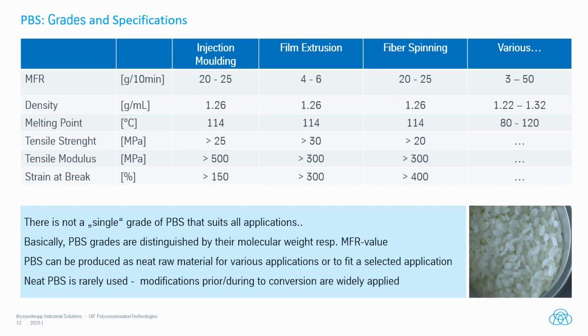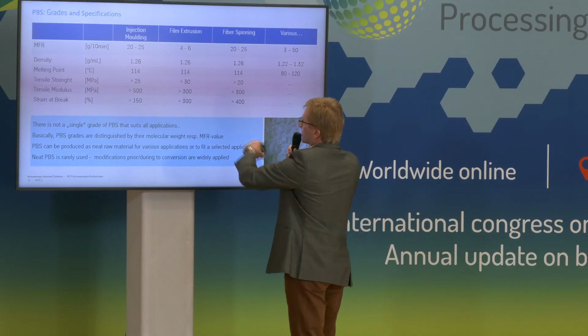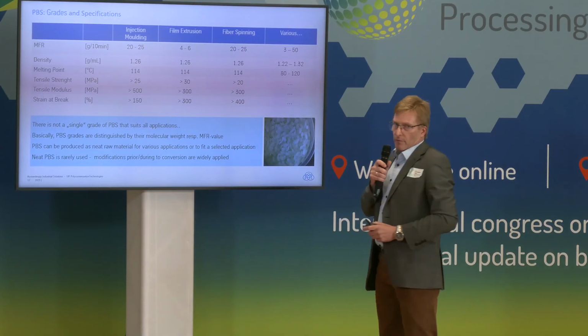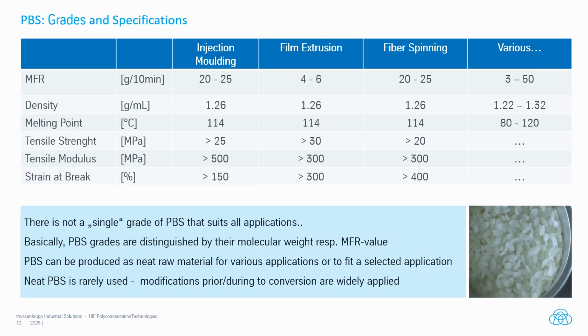As I said, PBS is not typically one grade. We differentiate different grades of PBS, for example, for injection molding, film extrusion, or fiber spinning. They are still all PBS, but they are slightly different, especially if you look at the strain at break, or the tensile strength, or the MFR, which is more or less directly related to the molecular weight. So to sum it up, there is not a single grade of PBS that suits all applications.